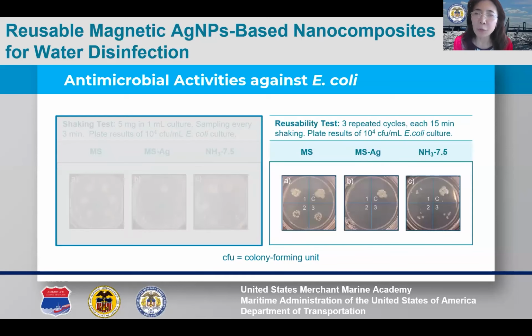To assess sample reusability, we repeated a 15-minute treatment on various cultures 3 times. The nanocomposites' disinfection abilities remained unchanged throughout the 3 cycles, as depicted in the typical plate results shown here.